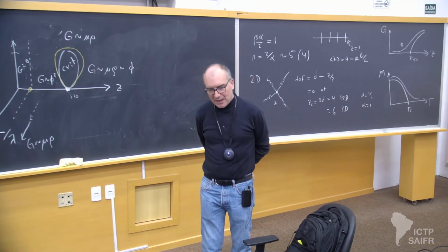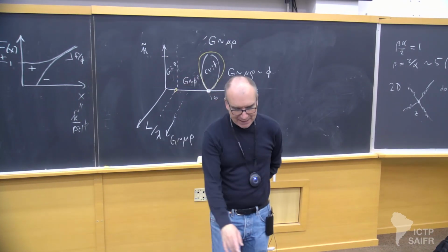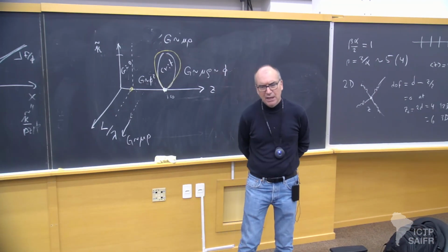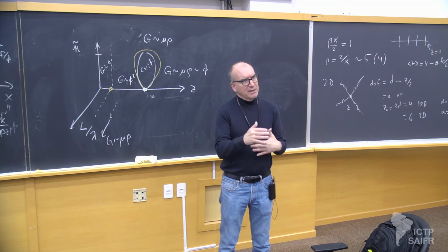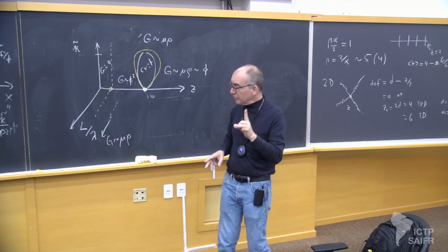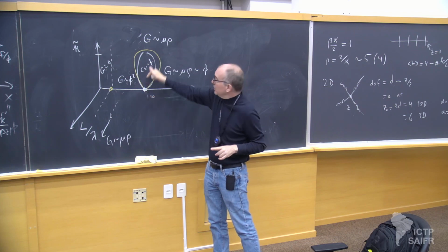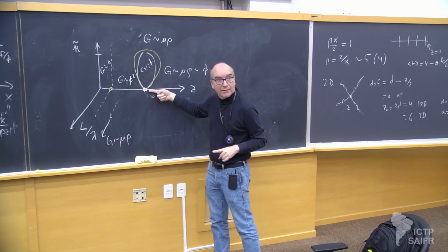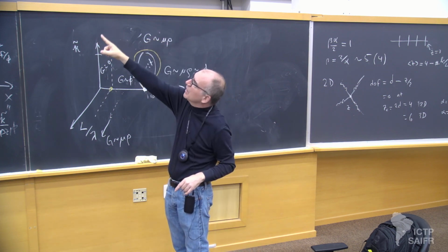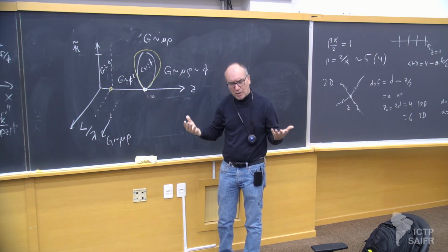So what's happening in that region is, as you deform the system, and maybe next time I can include a sort of cartoon to show this. I think it'd take me a little while to get it now. But in that region, as you deform the system, you get non-uniform deformations. Those are the non-affine deformations. What's interesting is not only do they grow in magnitude at this transition, as you approach it this way or that way, they grow, that peak grows. You might be able to make out the peak is suppressed as you go to higher bending rigidities. It's also suppressed by finite size effects, normal critical phenomena.